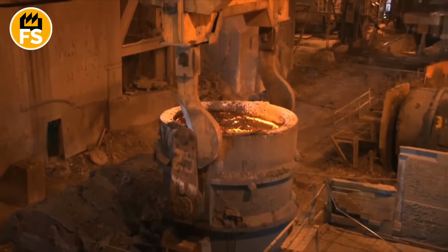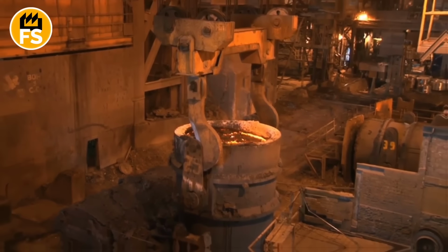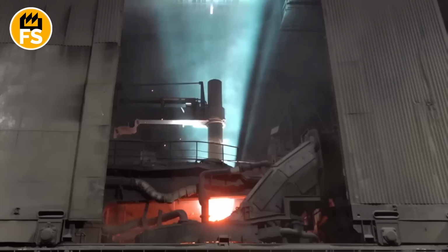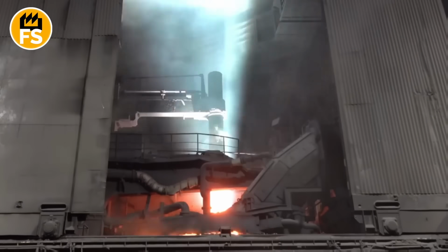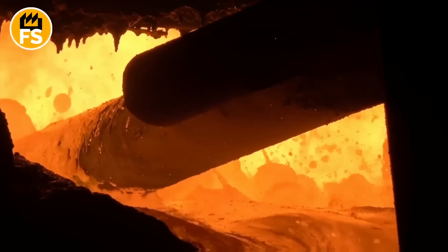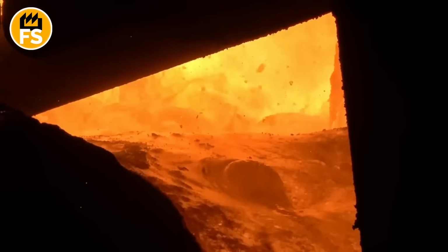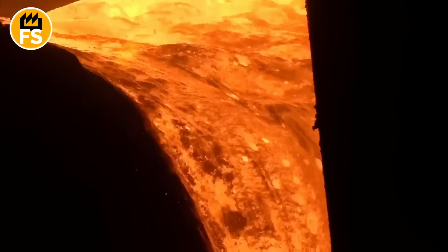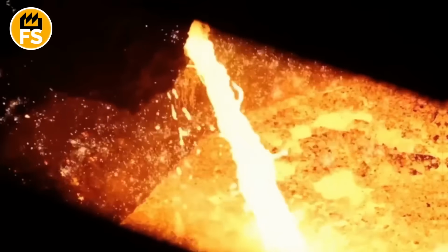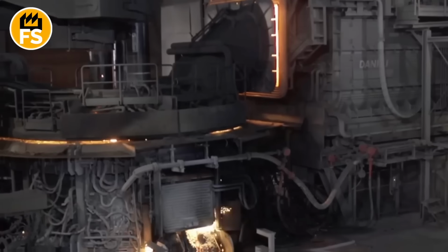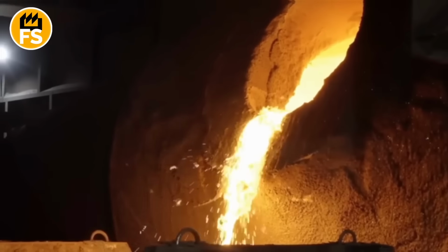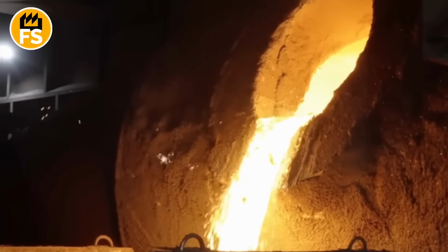Powerful graphite electrodes create an arc that heats the center of the furnace to approximately 5,430 degrees Fahrenheit. Under these conditions, ordinary rocks transform into active participants in the reaction. Silicon dioxide reacts with carbon, and as a result, oxygen is removed from the oxide. Gaseous carbon monoxide forms, while pure silicon transitions into a liquid state. The molten material is heavier than the surrounding charge, so it slowly settles to the bottom of the furnace, accumulating as a metallic mass.